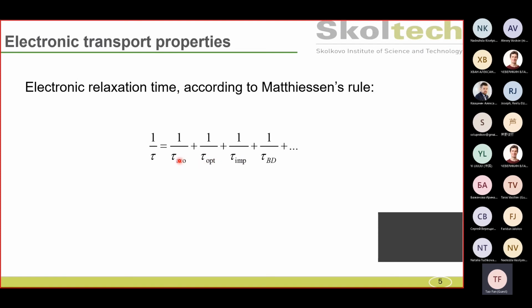For every scattering, the formula for each of them could be very complex. For example, for scattering from phonons, in order to compute it, you need very dense sampling in the reciprocal space for both electron states and phonon modes. So it could be very time consuming and resource limited. Luckily, we have simple models to calculate it.